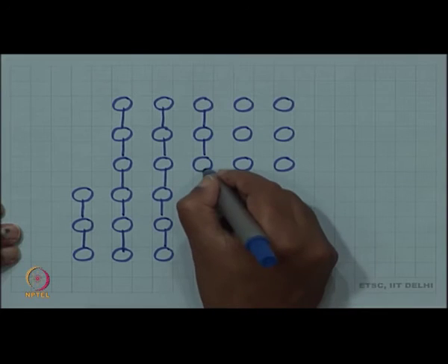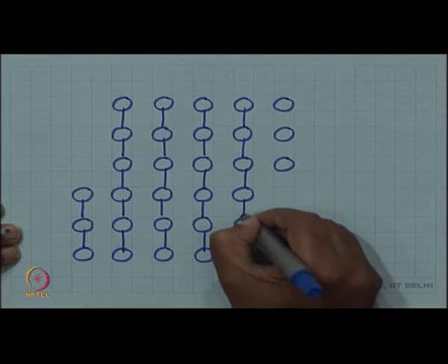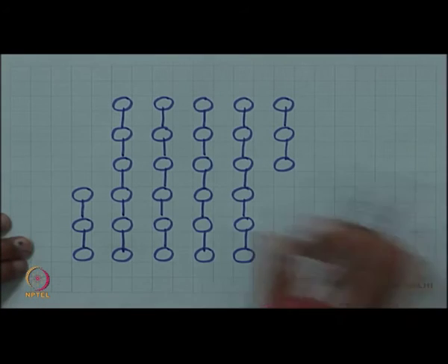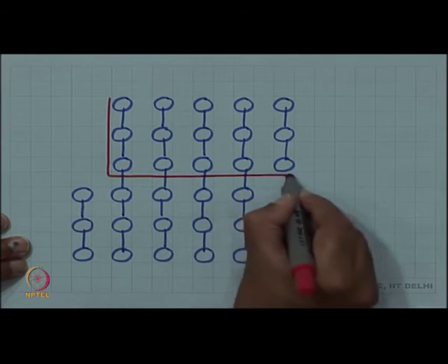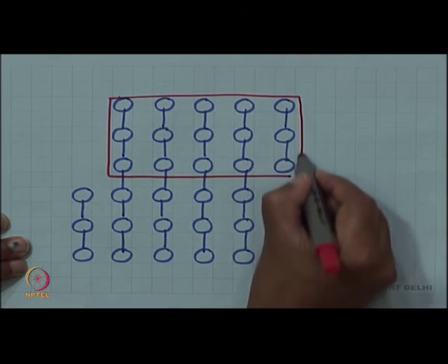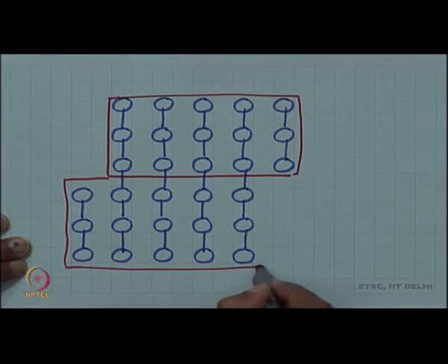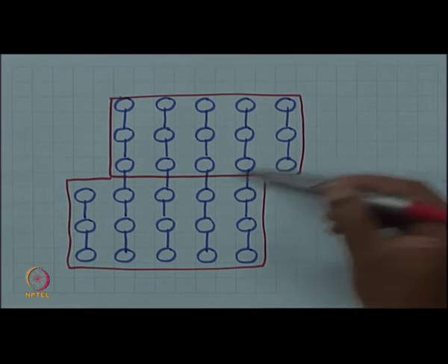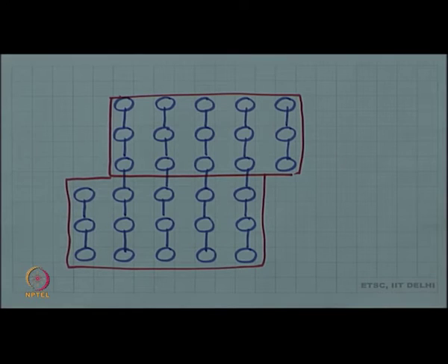in the end we have achieved the same configuration which we would have obtained by a complete single step rigid body deformation of the upper half of the crystal with respect to the lower half. However, it was achieved in steps such that in each step we were breaking only one set of bonds, and that is why the required stress was much lower.